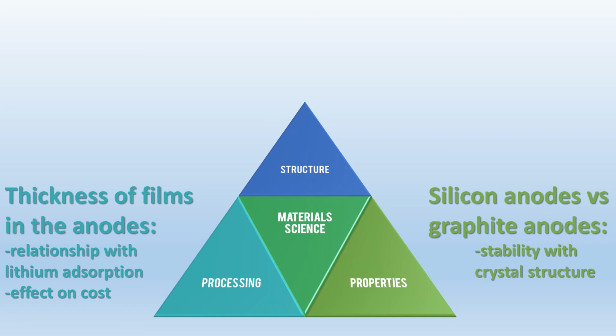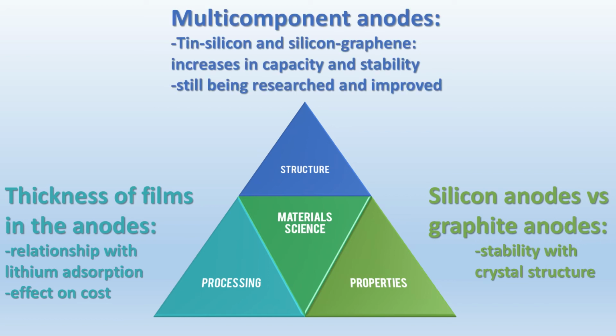This connects with structure. Several multi-component anodes have been developed to improve on current ones. From research, tin silicon anodes have been developed which yield substantial improvements in battery performance. They have 3 times the capacity of graphite anodes and are much more stable than silicon alone, which increases the lifespan of the battery. Only small amounts of tin are needed to gain these benefits. The increase in capacity is the most significant to improving batteries for electric vehicles.